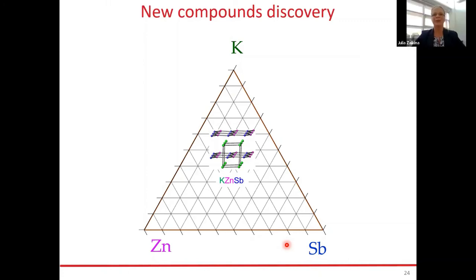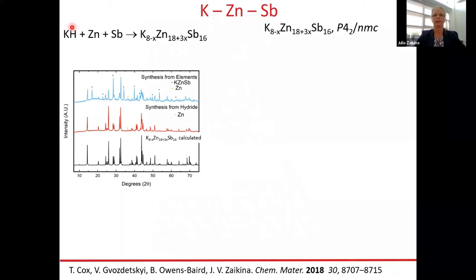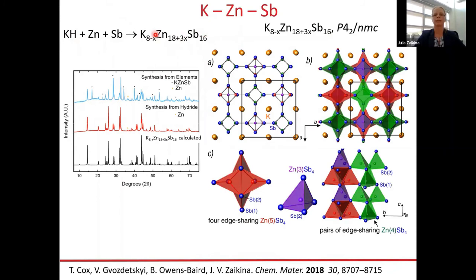Oh, okay. So I want to talk about the potassium system now. Similar situation we have. The 1,1,1 compound was the only one before we started looking into that system. And then by using the hydride route and trying different compositions, we discovered this compound, potassium 8-x zinc 18+3x antimony 16, which compositionally is roughly close to a 1:3:2 ratio.